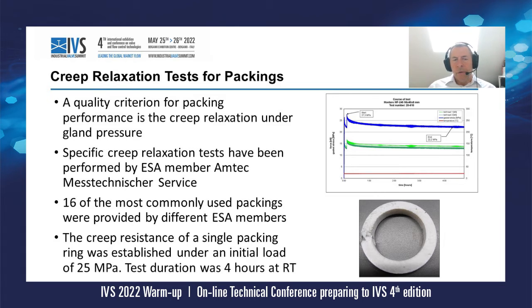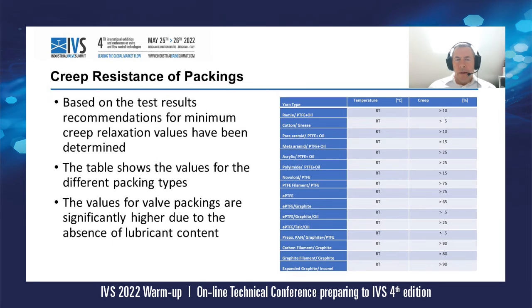The creep resistance of a single packing ring was established under an initial load of 25 MPa. The test duration and the holding time was 4 hours at room temperature. In the graph here you can see one of the test results. So the packing was submitted to the 25 MPa, then there was a short holding time, and then it was retightened to 25 again, and then the relaxation or the gland pressure loss over 4 hours was measured. Also, after finishing the test and when the rings were extracted, the extrusion was checked. Based on the test results, minimum creep relaxation values have been determined and put into a table, which you see here on the right hand side.